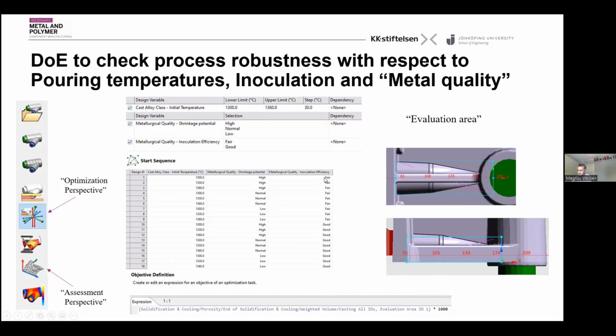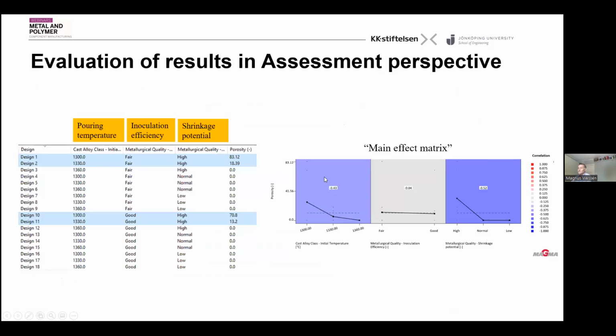Again, this is done in a few minutes of work, and then I get out lots of information. And as you know, I showed in the first slide that this was a good simulation. I didn't see any porosities, but now when I play around with these designs, I can see that there are actually 4 designs where I get some porosity. And of course, you can manually start to analyze the numbers. You can see that, for instance, if I have a low, say 1300 and 1330 degrees, together with a high shrinkage potential, then it seems that I get some porosity.